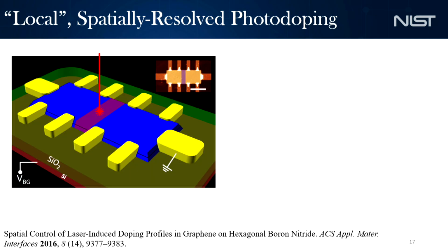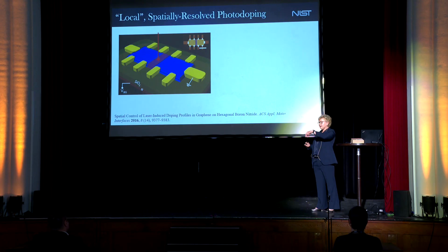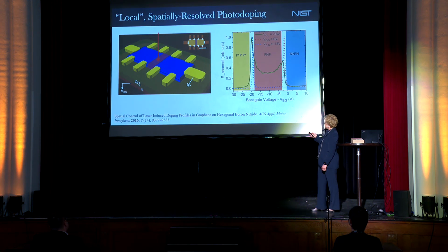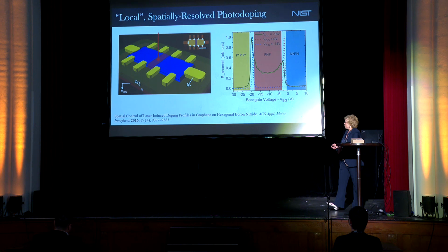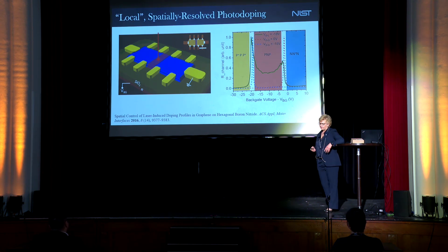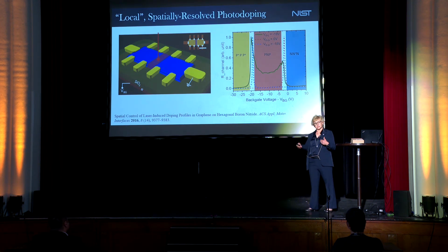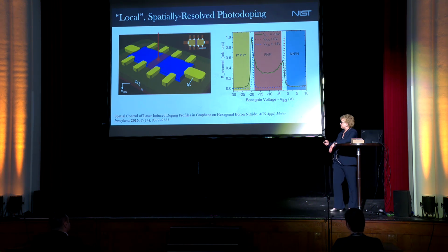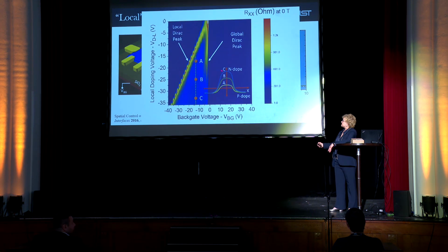Sorry about that. So then we're bringing our laser in, and we're moving the laser across the sample. And what we do then when we measure the quantum Hall again, we see that we have made different regions within the graphene device. What we believe, again, this is preliminary, is that we're making a lateral PNP junction. And again, this was also a French group, by the way. They also saw this, but they did not do the quantum Hall measurements to quantify or be certain about the thing.